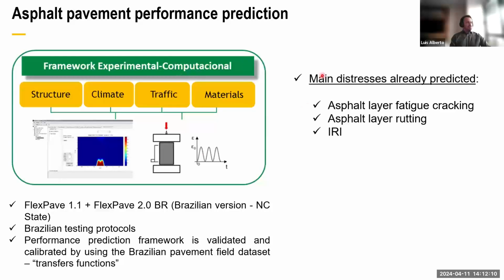And this is how we do it. The asphalt pavement performance prediction experimental-computational framework is composed of the FlexPave program, developed by North Carolina State University. It's based on viscoelasticity, continuum damage protocols, and some viscoplastic models. Here we have a Brazilian version where some models were integrated into the framework, especially for the unbound materials in Brazil, because in Brazil we have different unbound materials with different behaviors, so we need specific models to predict their behavior. That's why we have a Brazilian version of FlexPave 2.0.